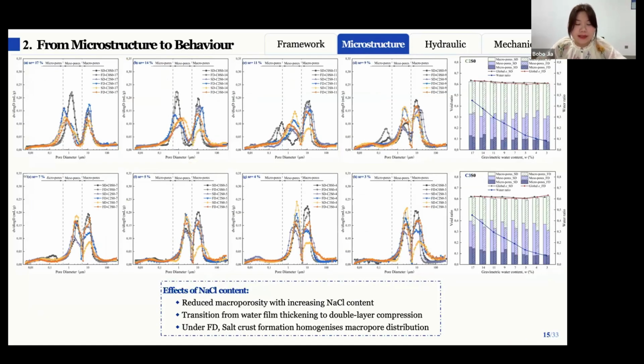So when further examining the influence of the salt content, here we can see C2 and C3, as the sodium chloride content is increased. An increase in sodium chloride can lead to a reduction in the proportion of macropores. And at higher water contents, the water film thickening effect dominates. Under faster drying, extensive sodium chloride crystallization at the top of the sample leads to the formation of a salt crust, which reduces the differences in macropore distribution.